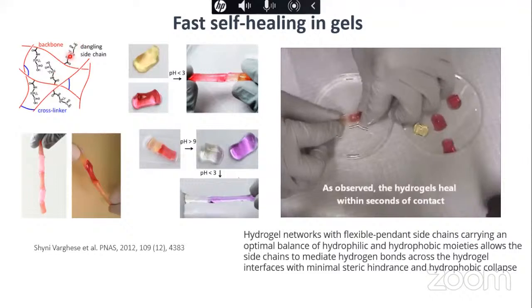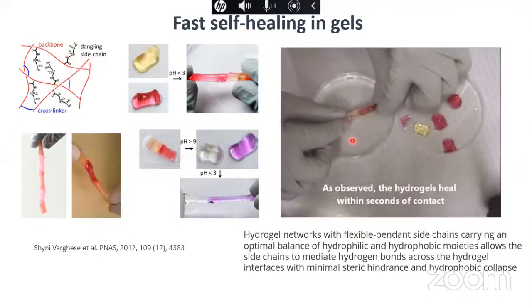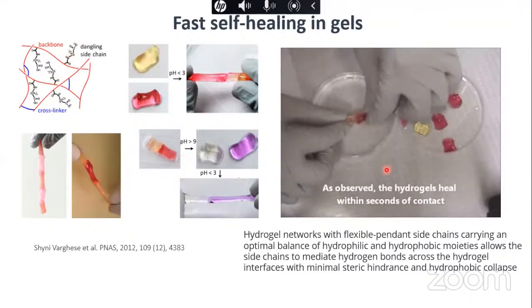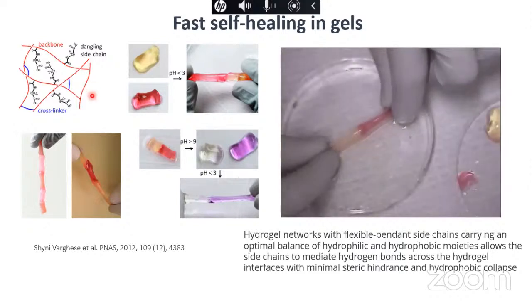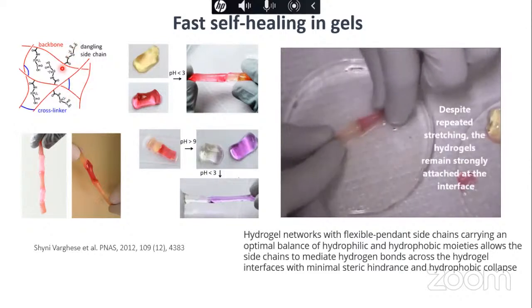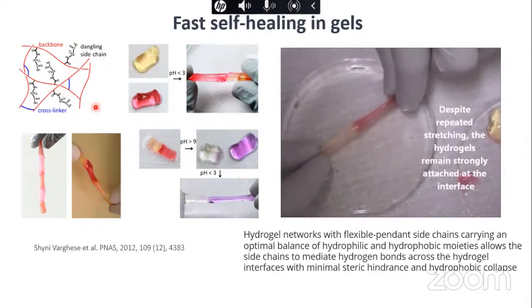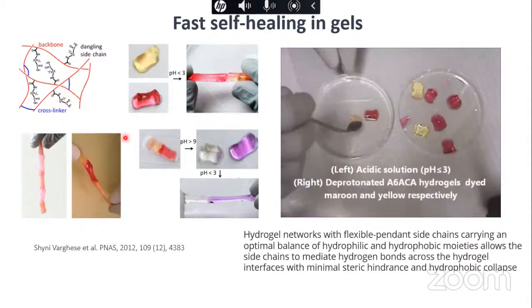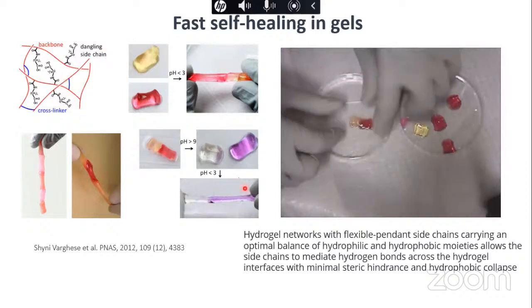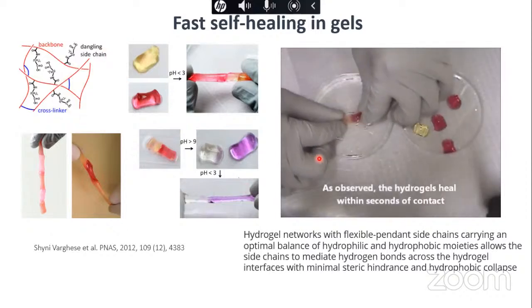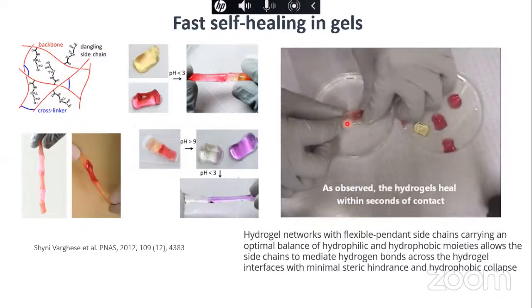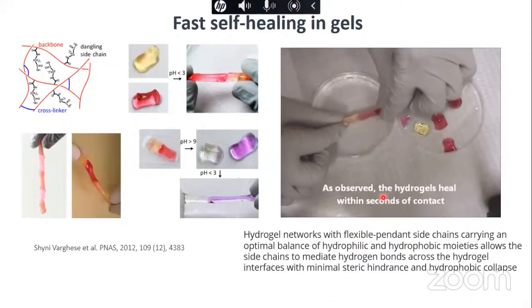This is because these hydrogen bonding groups at the crack, where you are basically breaking them, when you put them together in a buffer kind of solution, there is a lot of diffusion. These hydrogen bonding groups can move a little bit because there is a lot of solvent also, since these are gels. The hydrogen bonding groups move, and then again they reform the hydrogen bonding interactions to self-heal. So this is the mechanism in this particular case.